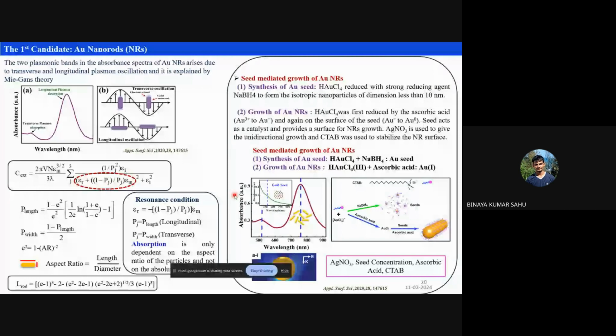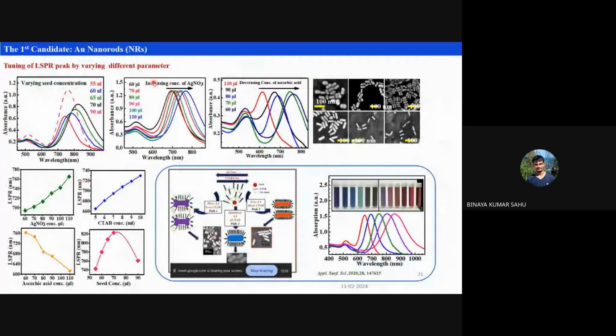And during the seed mediated growth, there is a liberty of using various chemicals. You can play around with different chemicals like HAuCl4, then silver nitrate and CTAB. Because I want this peak in a very particular position, or I can vary this peak as per my requirement. To obtain that, we did various experiments, and we were able to tune the SPR peak to different positions.